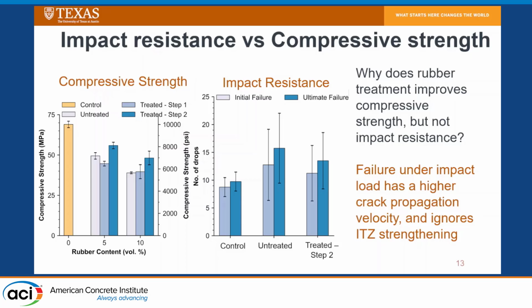mechanisms. When you're talking about compressive strength, you're talking about a static load, so therefore our cracks tend to propagate around our ITZ. However, when we're talking about an impact load, it's a dynamic load. It's a very fast crack propagation. And in this case, it may not necessarily go around the ITZ. So it's ignoring the strengthening that we have in our ITZ, interfacial transition zone.